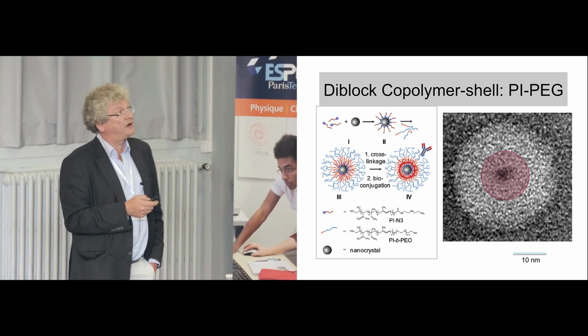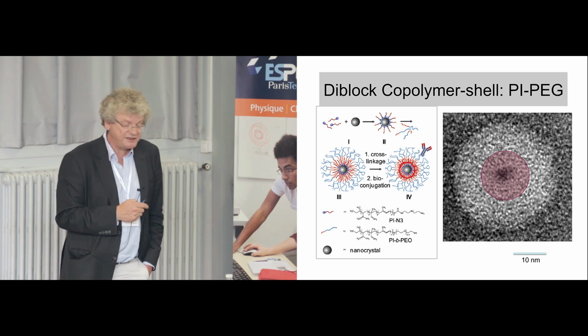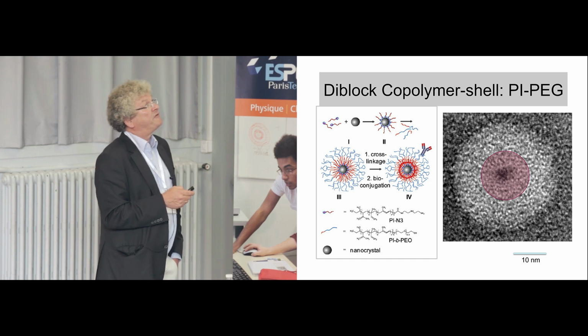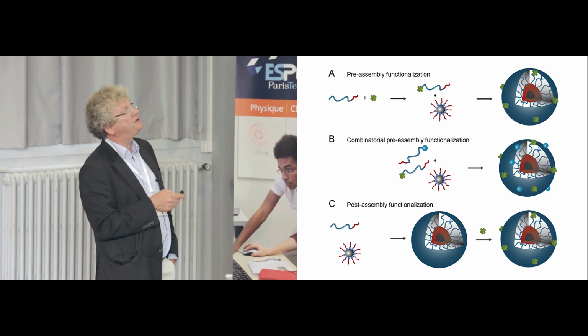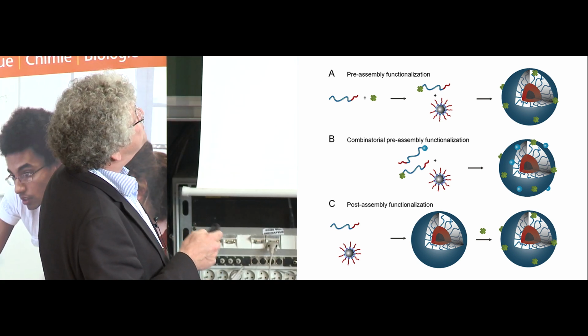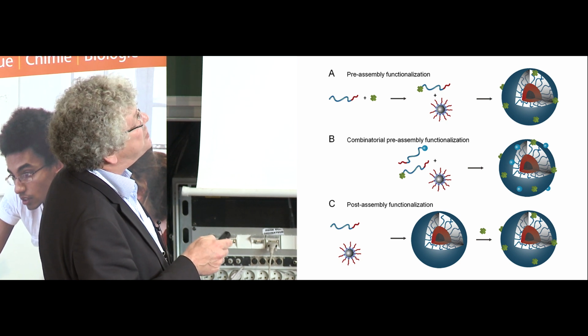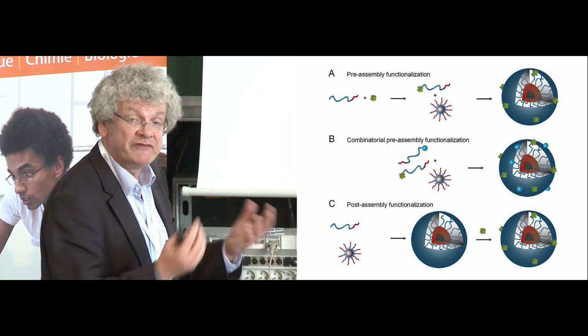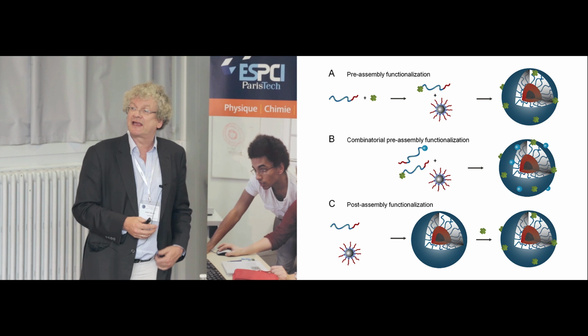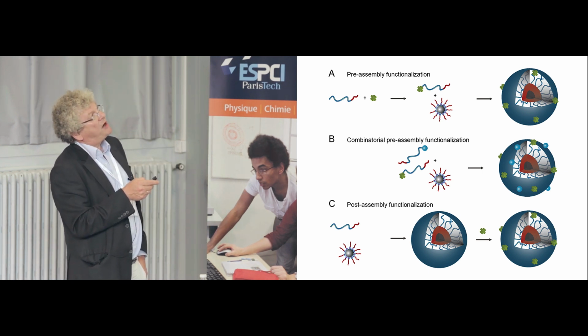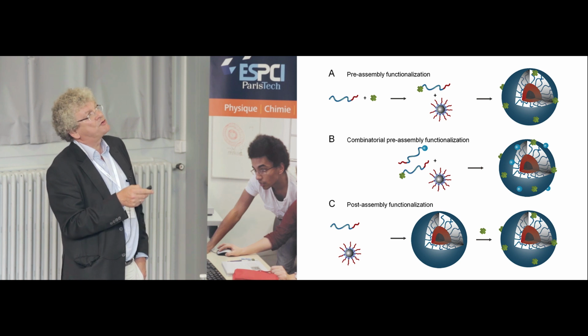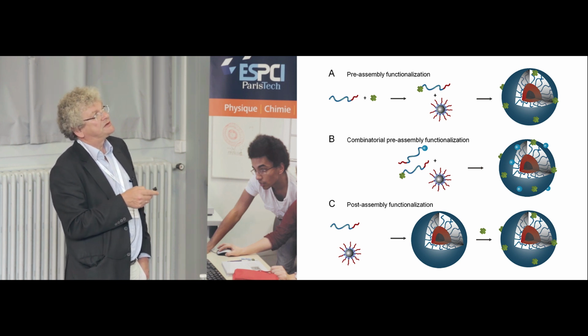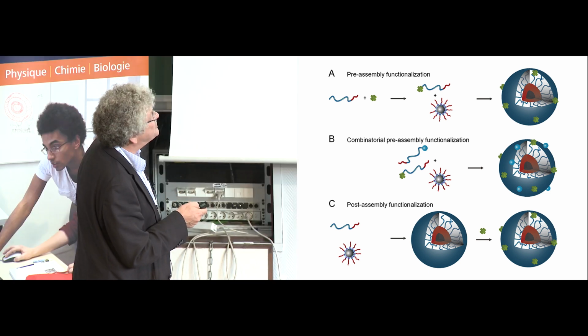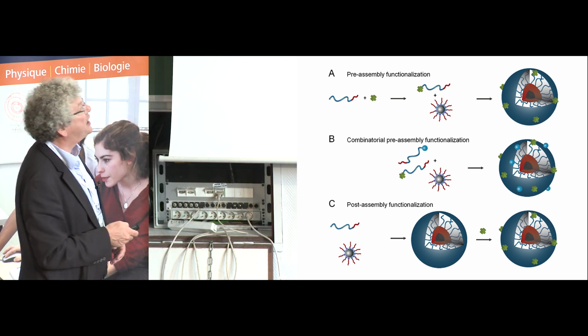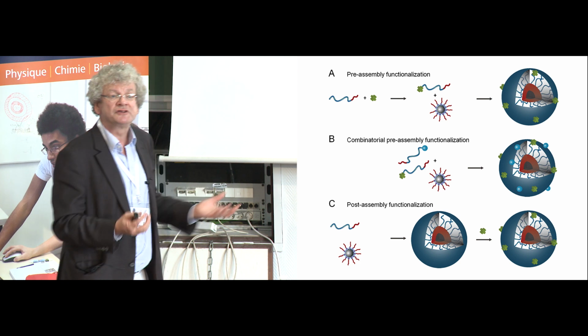One of the nice things of this type of encapsulation is that you can do a very nice optimization of these systems, and you can apply combinatorial approaches. Because we have what we call pre-assembly functionalization, that means we take just a diblock copolymer and functionalize this. This you can very easily do, and you can follow your progress by typical chemical analytical processes. So we have partially these functionalized diblock copolymers, and during self-assembly, they are just incorporated here. And so we can mix different types of such pre-functionalized polymers and different concentrations, mix them with non-functionalized ones, and so you can form various patterns of recognition molecules at the surface.